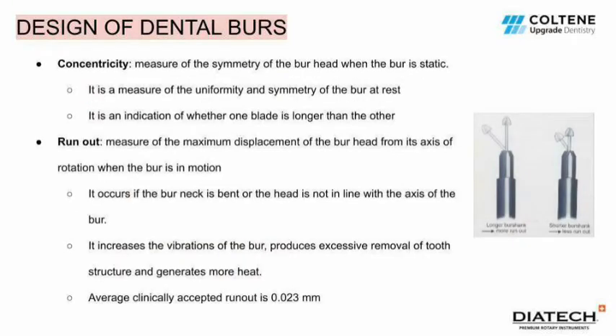The next two parameters are concentricity and runout. Concentricity is a static measure, while runout is an active measure. Concentricity is a measure of the symmetry of the burr head when the burr is static. It measures the uniformity and symmetry of the burr at rest and is an indication of whether one blade is longer than the other. Runout, on the other hand, is a measure of the maximum displacement of the burr head from its axis of rotation when the burr is in motion.